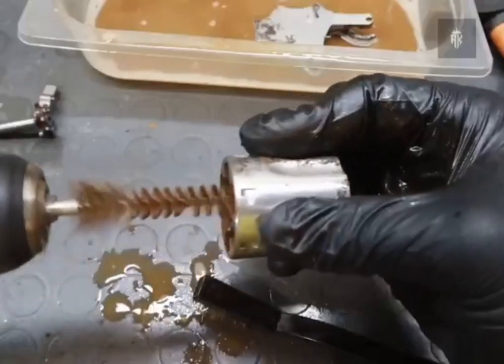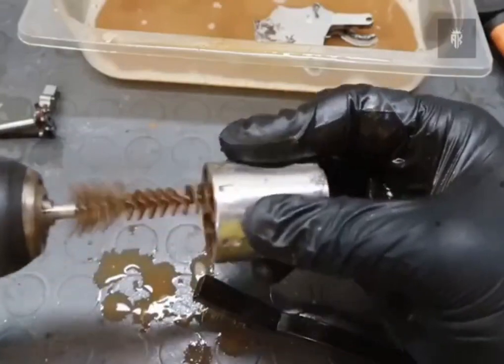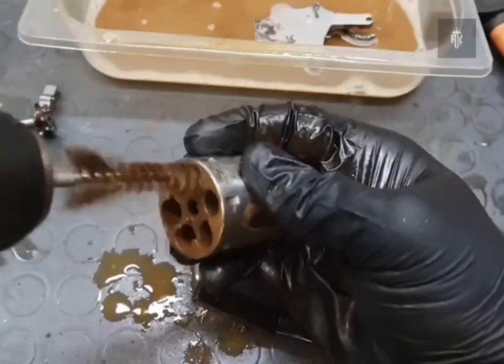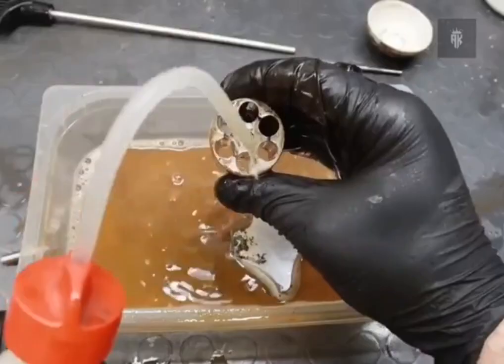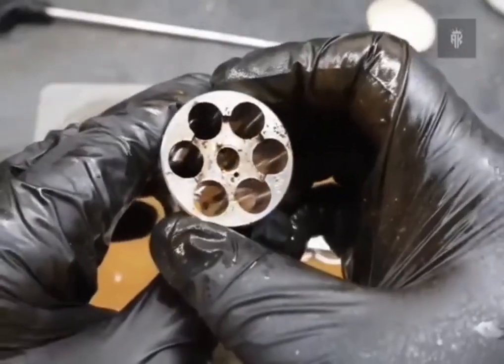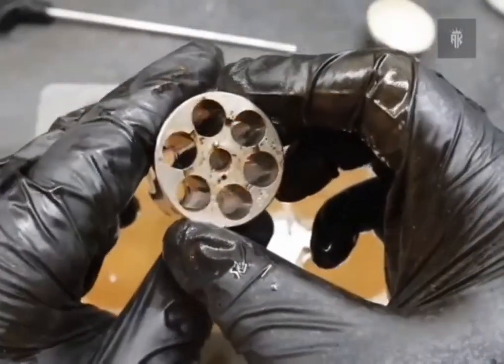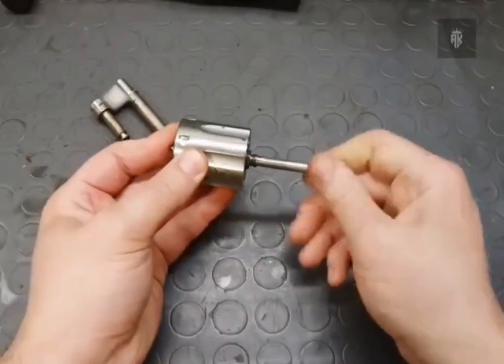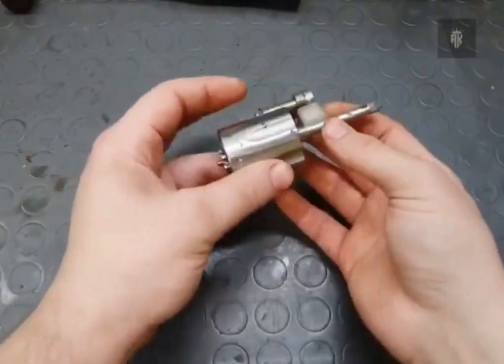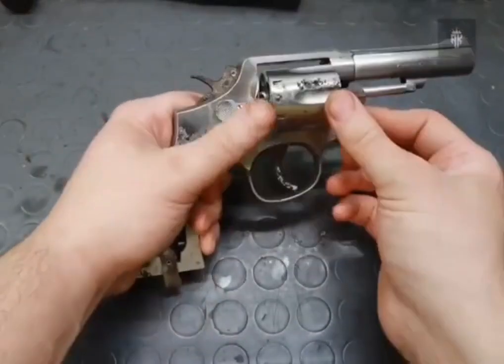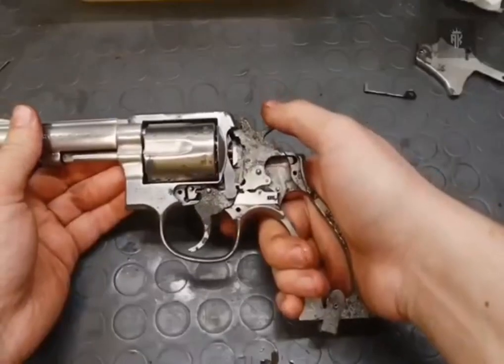For the revolver, things are slightly different. While the barrel is still in great shape, some chambers of the cylinder have some deep pitting on their outer surface that can weaken them. If these had been on the inside surface, the most stressed one, the chambers wouldn't be safe to fire. Being on the outside, reducing the operating pressure a bit should compensate for the weakened structure. For this reason, I'll only be attempting to use 38 special loads in it, since the operating pressure is half that of the 357 Magnum.